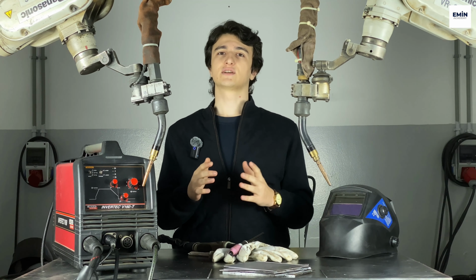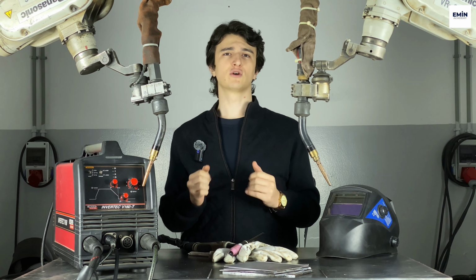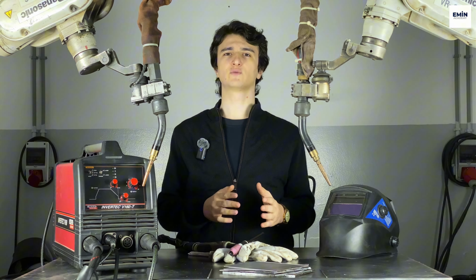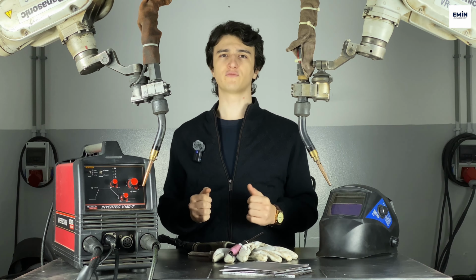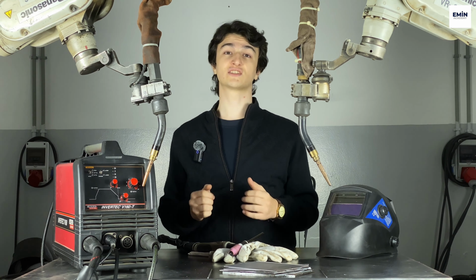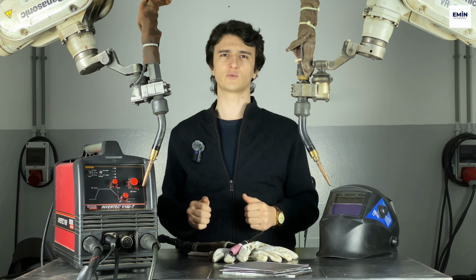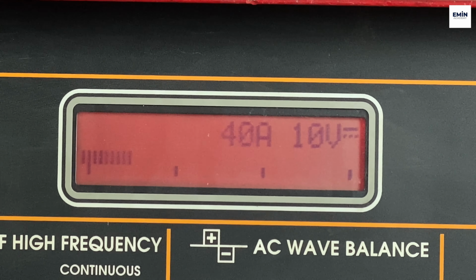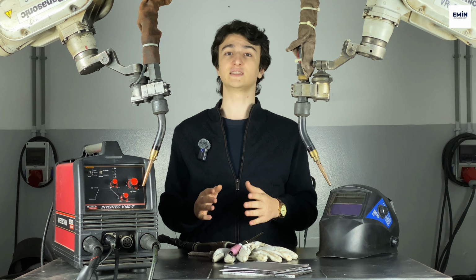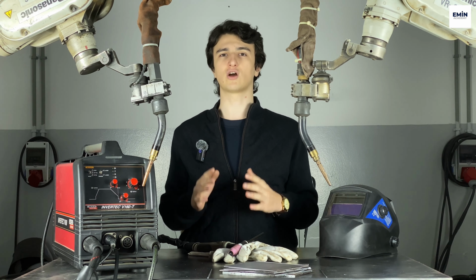Thin carbon steel conducts heat quickly and also deforms very easily. So, do not try to complete the weld in a single pass. Weld in short bursts, stop and then move forward. This method prevents the sheet from overheating and reduces warping. Using pulsed current keeps heat input under control and allows for a narrower, more controlled weld. Excessive heat causes burn marks, wide welds, deformation, and loss of strength in carbon steel.